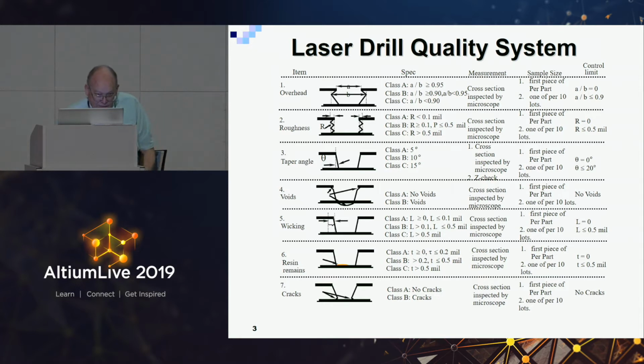And you can see down here: overhang, roughness, taper angle, voids, wicking, resin remains, and cracks. And here are some measurements, some specs, A, B, and C, control limits, and sample size. I recommend you copy this, and if your board has laser drilled holes in it, that this be checked and entered into your manufacturing specs in terms of what you want those holes to look like, because there are no IPC documents for them. I don't know if the European Space Agency has them or not. I don't know a lot about European specs.